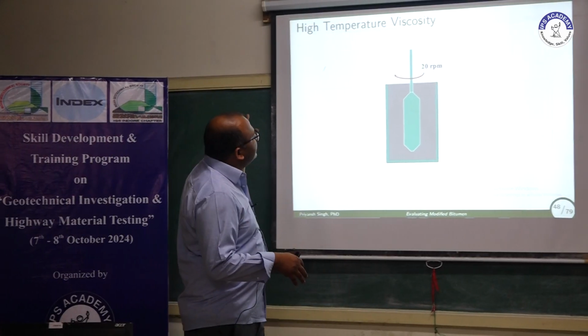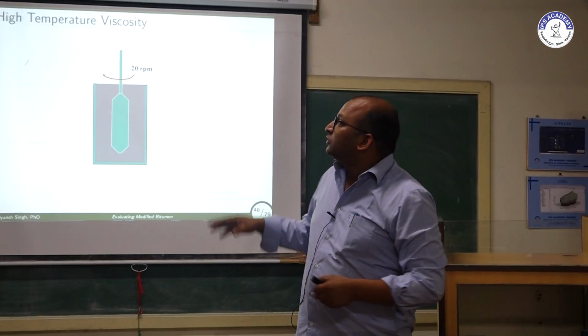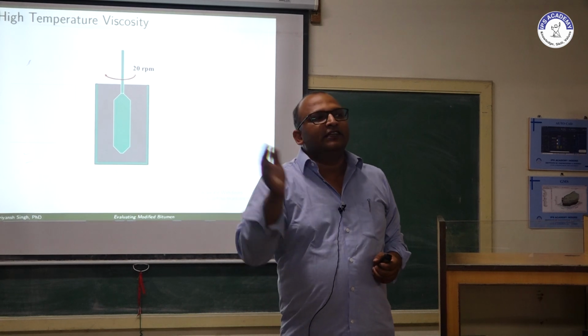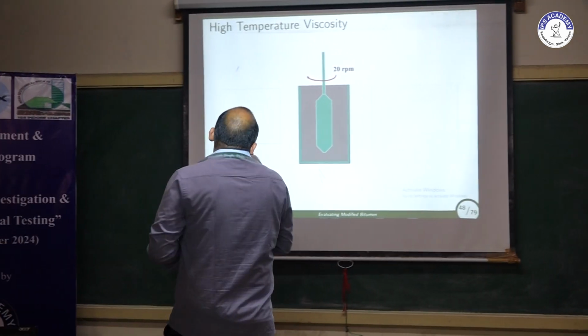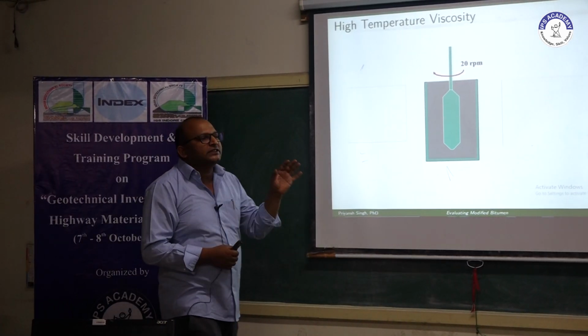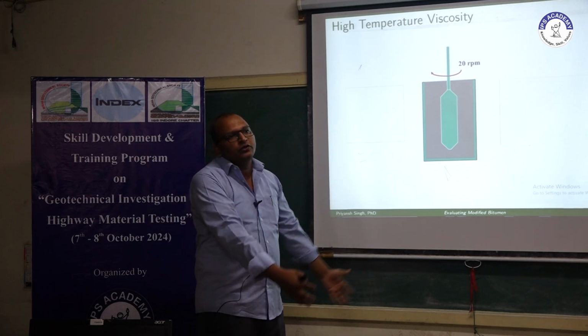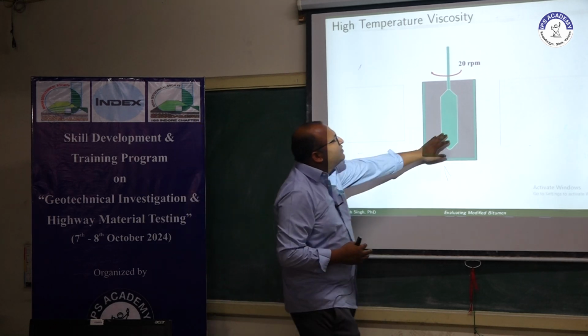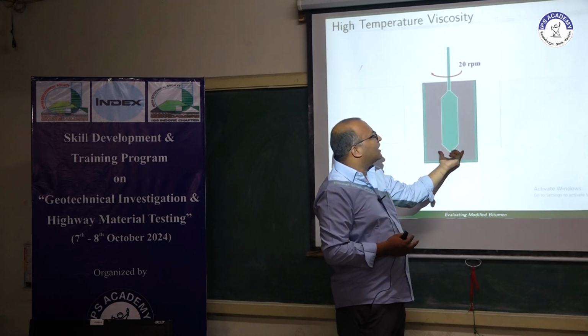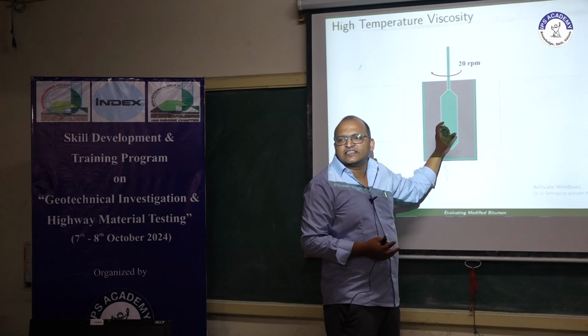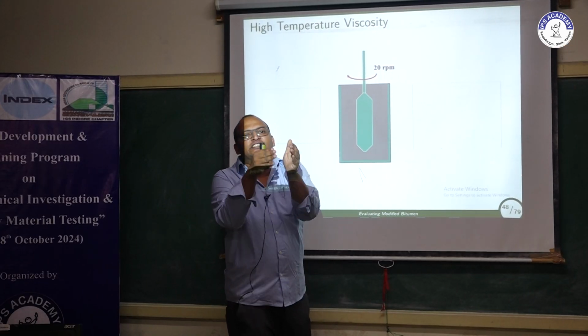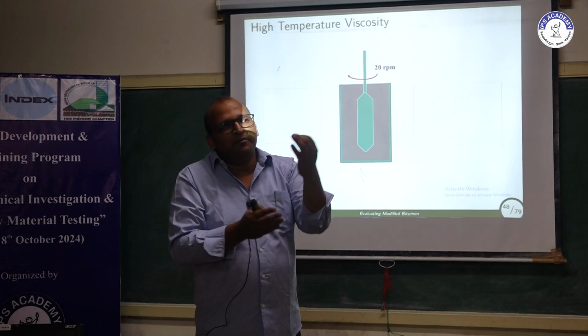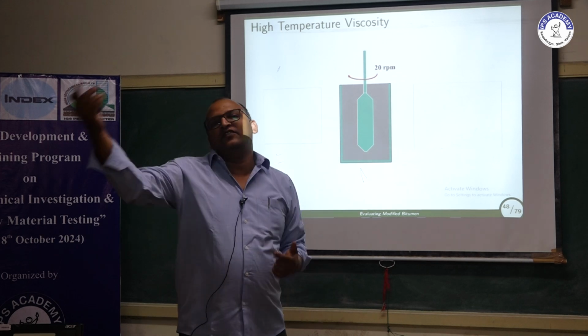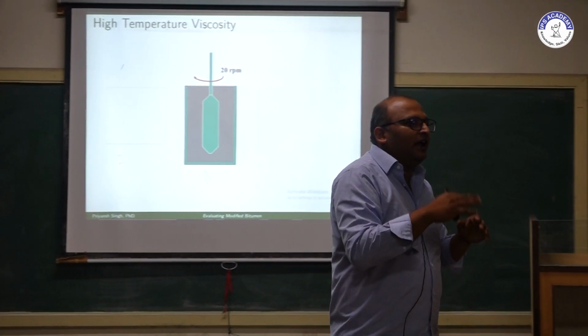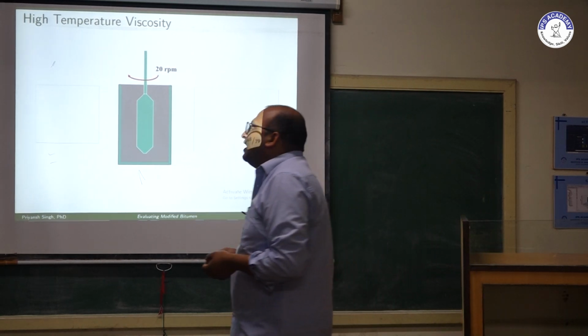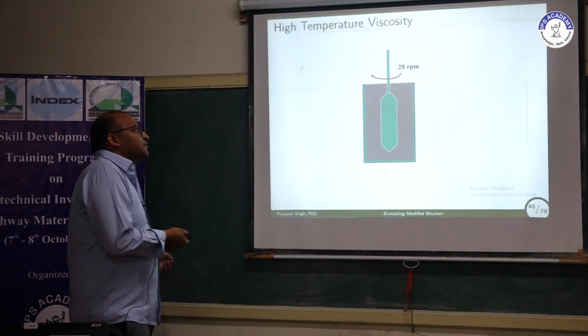In order to check that, first let's see the set of tests and how they will be connected. The first test is the high temperature testing, around 135 degrees Celsius or maybe 160 degrees Celsius, that means at your mixing and compaction temperature. This test is done by a rotational viscometer. I will not go into the details of the rotational viscometer, but it has a spindle. You will have fluid filled in a container, and this spindle is going to rotate inside the fluid. Your motor will try to rotate it with a constant speed of 20 rpm or whatever is desired. The amount of energy required to rotate the motor will signify your viscosity. If a higher amount of energy is required, the viscosity is higher, and if lesser energy is required, the viscosity is lower.